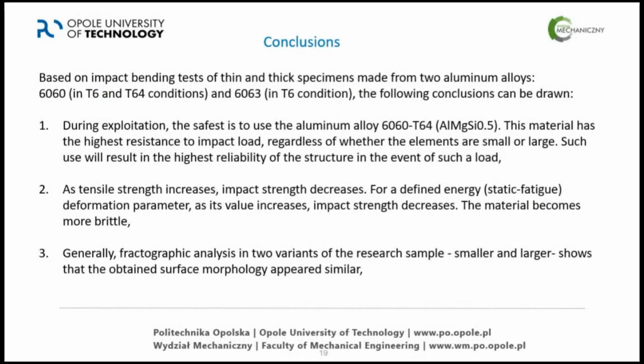And in the end, the conclusion: for safety, it is recommended to use the aluminum alloy 6060 T64. This material has the highest resistance to impact load, regardless of whether the elements are smaller or larger. Such use will result in the highest reliability of the structure in the event of such load. As tensile strength increases, impact strength decreases. For a defined energy, static fatigue, in the right-hand figure, the deformation parameter value increases, impact strength decreases. The material becomes more brittle.